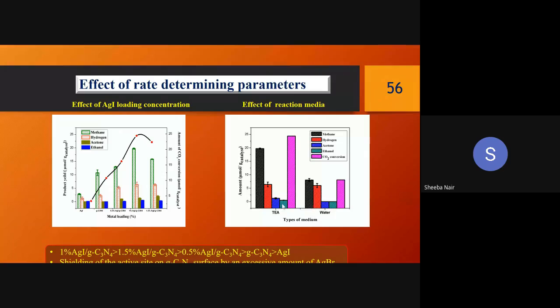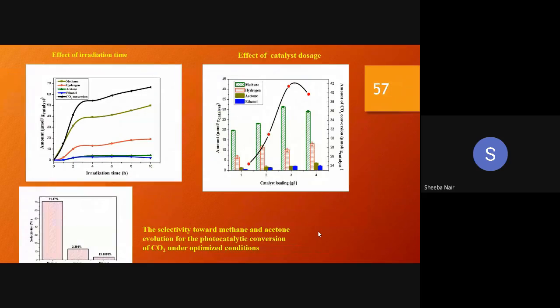In addition, you can see that here one more component is present, which is the ethanol. Just see here, this was an accidental result. Even though its composition was very meager, we never expected that we'd get ethanol. And as I told you, we never aimed at the selectivity of the material. So ethanol was an indication that this kind of catalyst, when improved, can be used for the production of ethanol also. Then coming to its selectivity and yield, we are yet to confirm it. Ethanol is better than your acetone. We are yet to explore the mechanism of this ethanol formation.